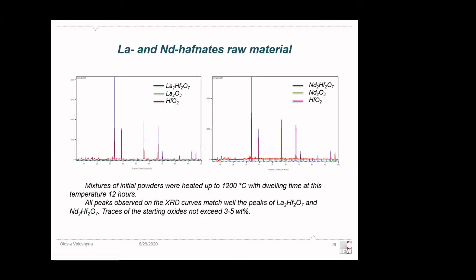So at the moment, what we achieved is that we have the proper procedure for obtaining the raw material of lanthanum and neodymium hafnates with a high content of the main phase, and traces of the starting materials not exceeding 3 or 5%.